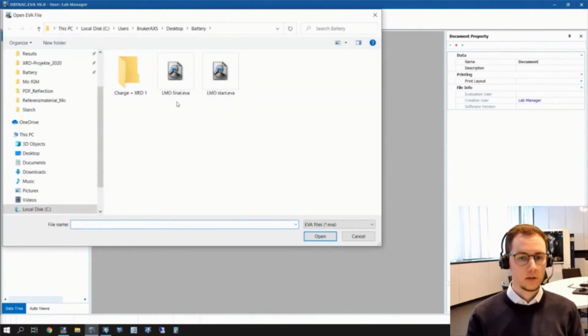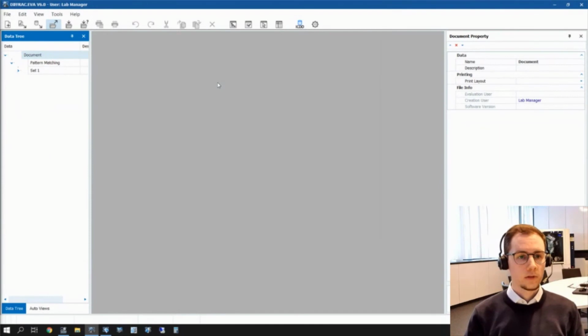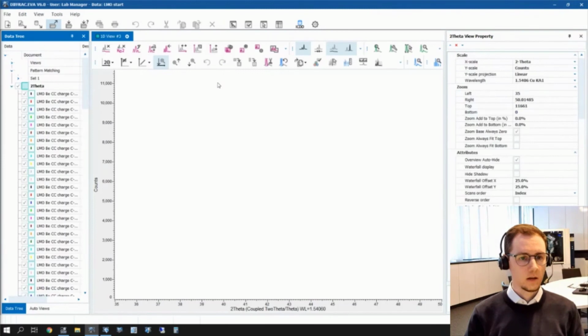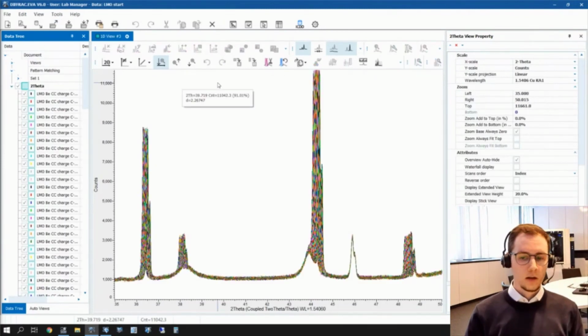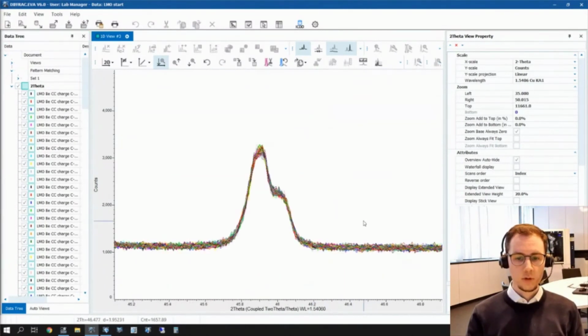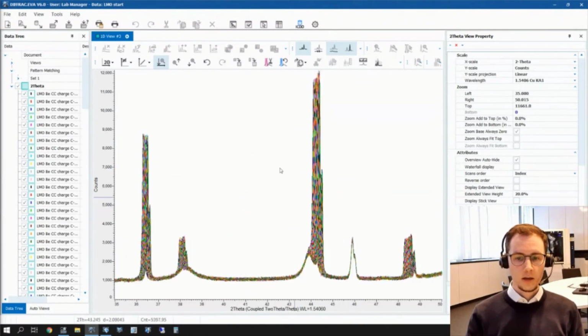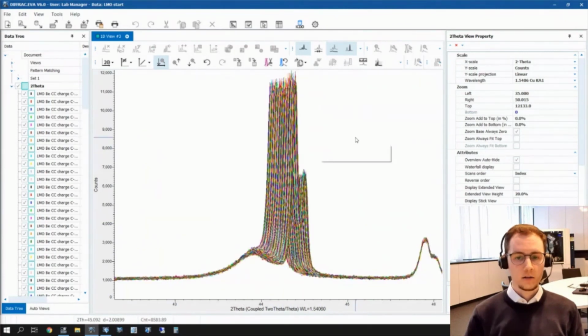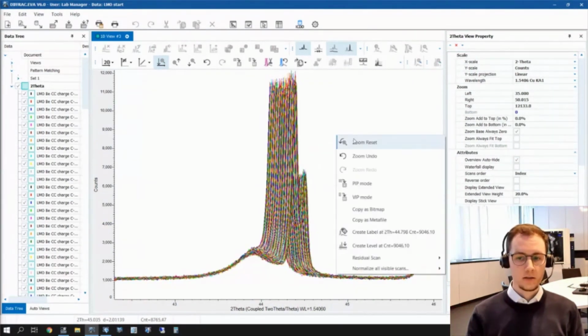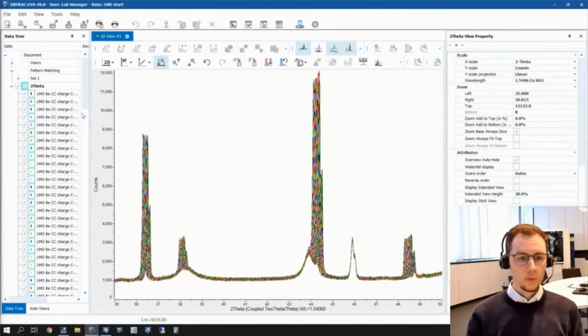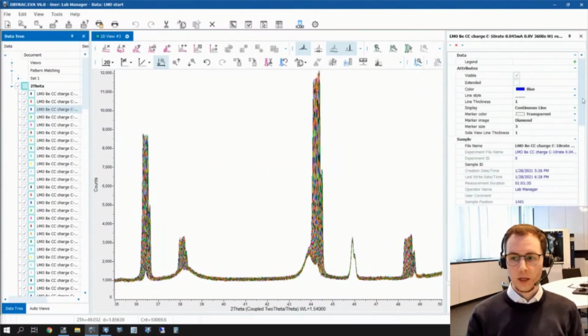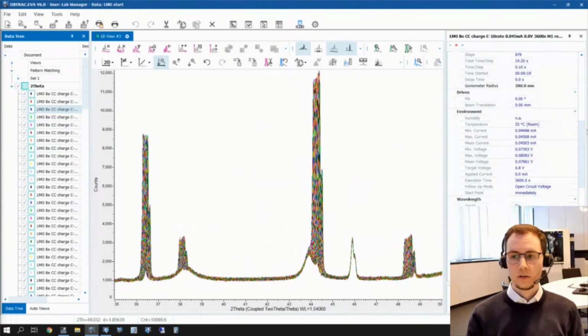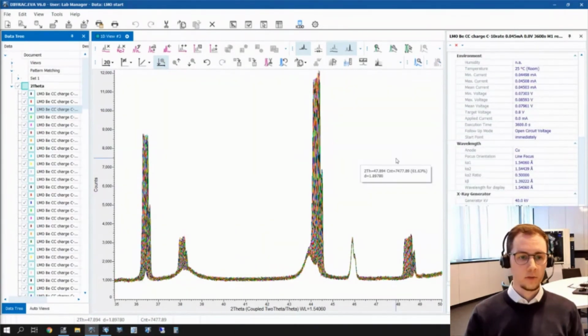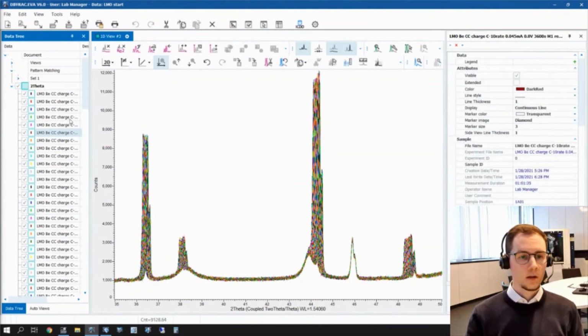I've prepared a document already where we have a set of scans. This was recorded some months ago, about 140 scans. And we see here one peak which is not moving. This is actually the beryllium peak of the window. And we see a lot of peaks that are moving here, and this is the lithium manganese oxide. For every subscan, we have the information of the current and voltage. So we have all this information available for every subscan.